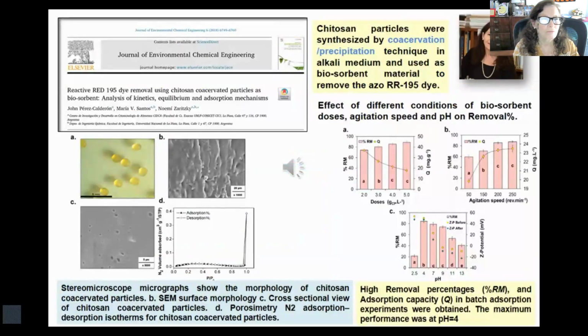In this work, chitosan particles were synthesized by coacervation precipitation technique in alkali medium, and they were used as biosorbent material to remove the azo dye. We can see the stereomicroscope micrographs and the scanning electron microscopy surface morphology. The particles show high removal percentage and adsorption capacity. The maximum performance was at pH of 4.